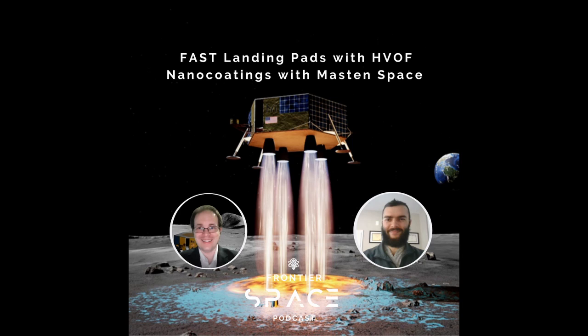That lets us keep the thickness of the pad fairly thin, about 1.25 millimeters for something the size of the Blue Origin Blue Moon lander. That was the driving force there. And then the material is thermally stable enough that it can take the heat flux and the temperatures of the gases. An interesting point on the structure is that because it is so thin, it's not designed to take the weight of the entire landed lander. So the landing pads would actually crush through the thin pad, and that's just part of the design.